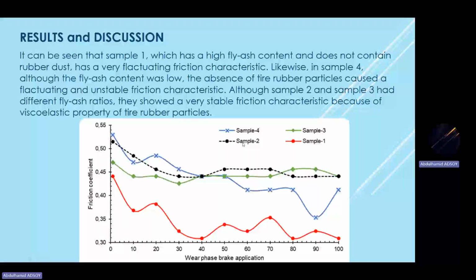But samples 2 and 3 show a more steady friction coefficient. Now, although samples 2 and 3 have different fly ash ratios, they both showed very stable friction characteristics because of the viscoelastic property of tire rubber particles.